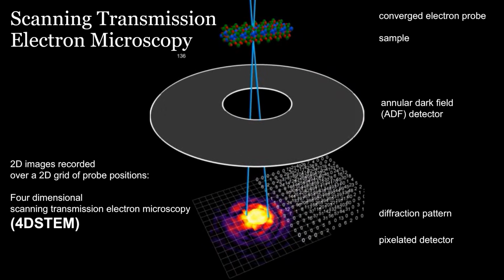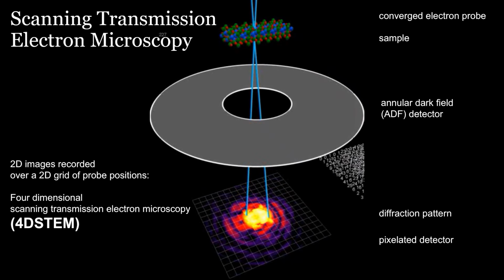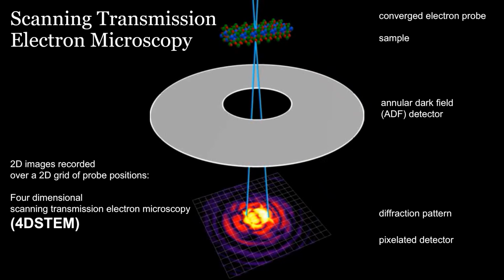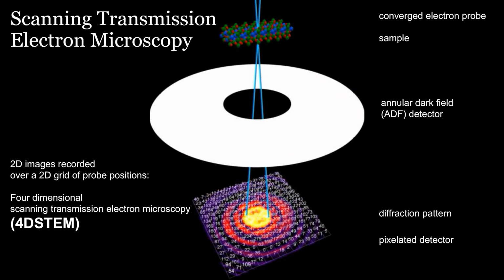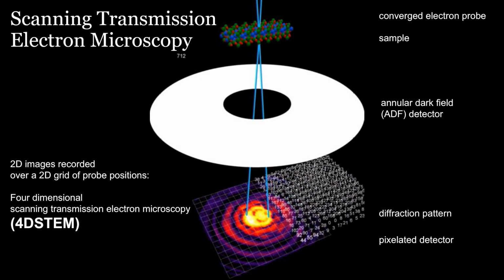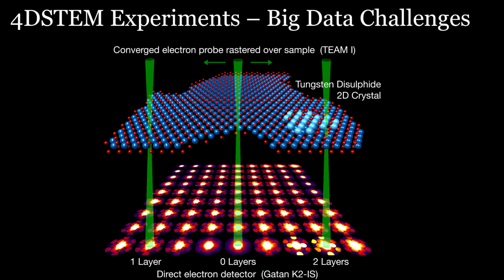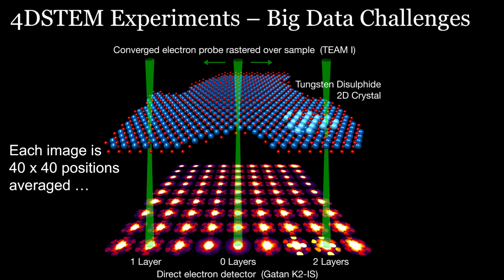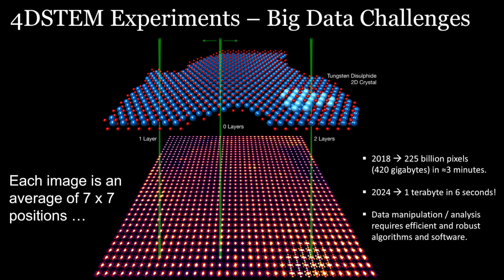So the resulting data sets are enormous. They're 4-dimensional. We have 2 spatial dimensions and then 2 reciprocal space dimensions here. And that gives the technique its name, 4D STEM, for the 4-dimensional data. So this is one of my earliest 4D STEM experiments. This is showing tungsten disulfide in our team microscope at Berkeley. And this is giving sort of a picture of what the diffraction patterns look like. But here I've averaged 40 by 40 probe positions. If I take a step back and show an average of 7 by 7 probe positions, you start to grasp the scale of the data here.